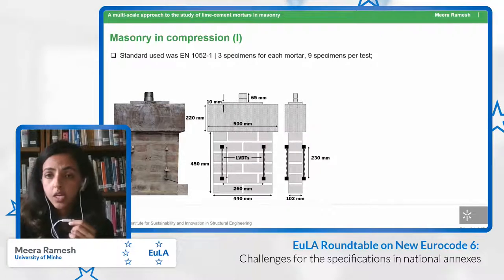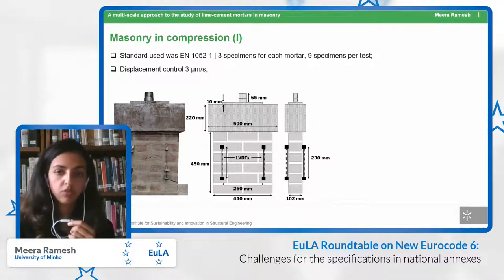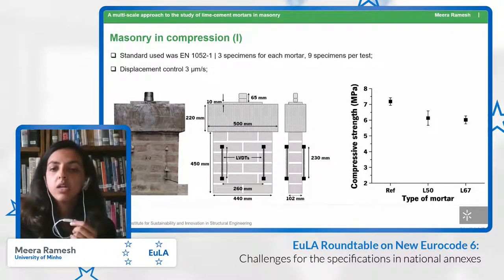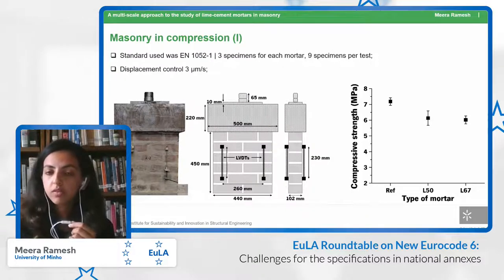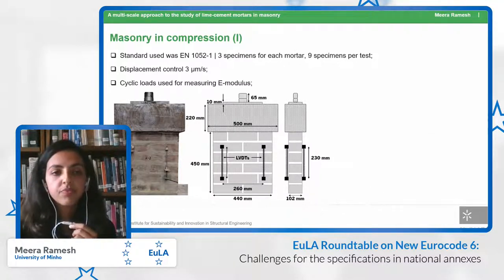The first property that we studied was masonry in compression. We used the standard EN 1052-1, and we used three specimens for each type of mortar. We used the method of displacement control, and we found that the mortar did have an influence on the compressive strength of masonry, but it was relatively minor. So between the reference mix and L67, all values ranged between 6 to 7 megapascal.